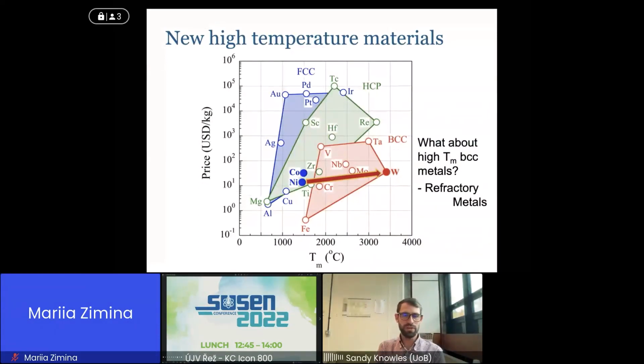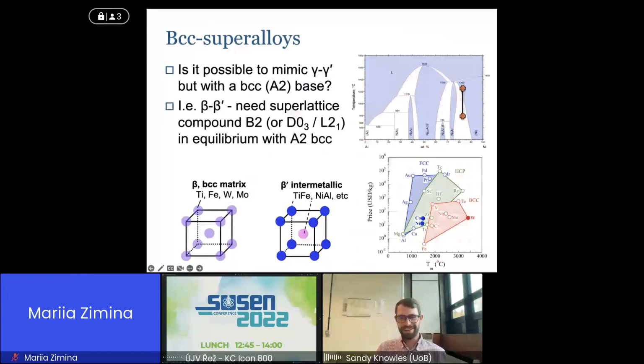Going there, we've run out of FCC metals. We can't take a direct analogy to nickel-based superalloys, but we consider what about some of the other high melting point metals? We could jump, rather than being FCC, to BCC. We have all of what we call the BCC refractory metals, particularly things like tungsten. So why not consider these high melting point metals? And we asked the question: if this gamma prime microstructure is so effective, is there an analogy to consider a BCC based system, a beta prime? This is what's kept me busy for coming up to 10 years now, working on this concept of BCC superalloys. We're really trying to take inspiration from gamma prime, but now that we've changed to a BCC base, we also need to change our intermetallic species.